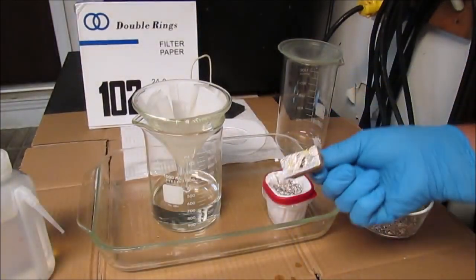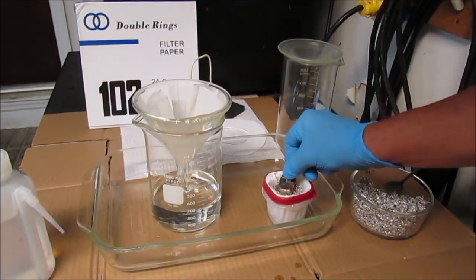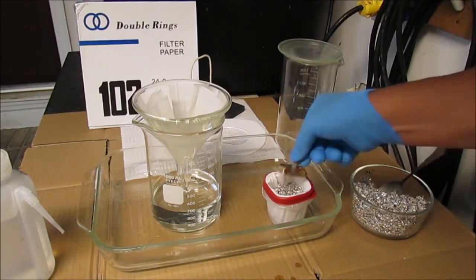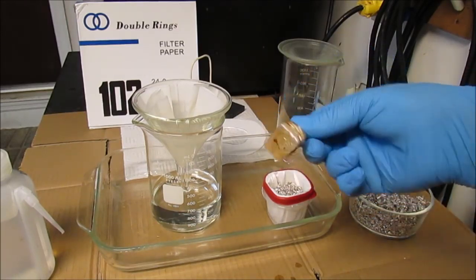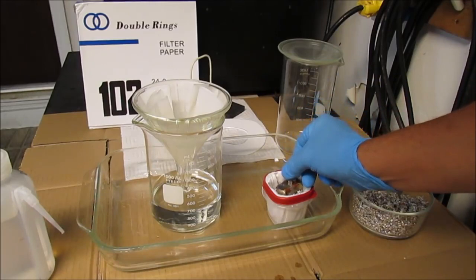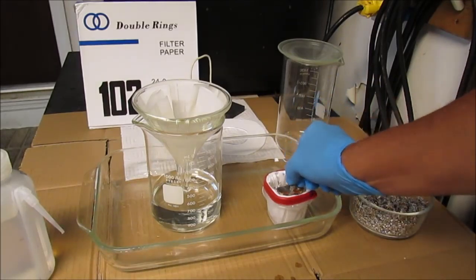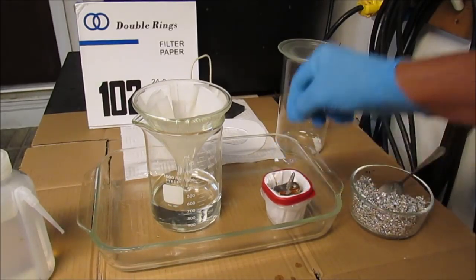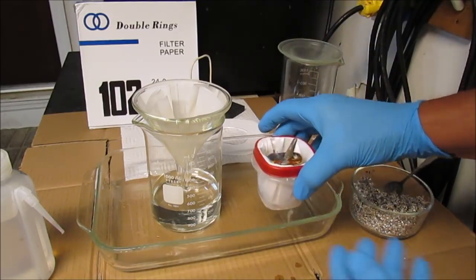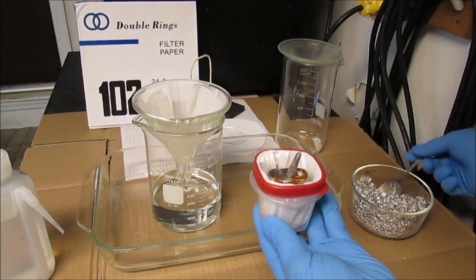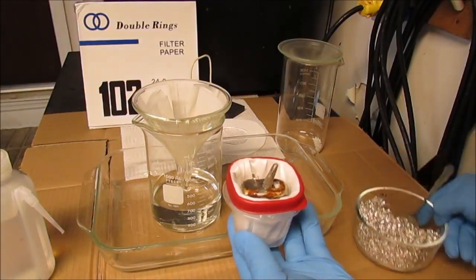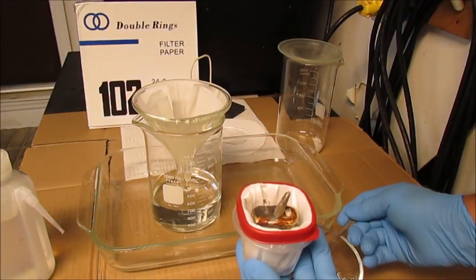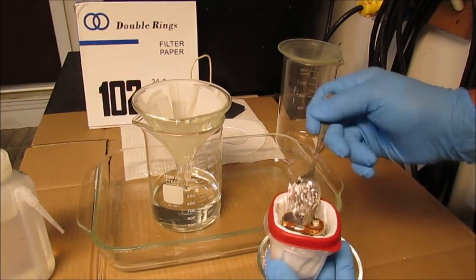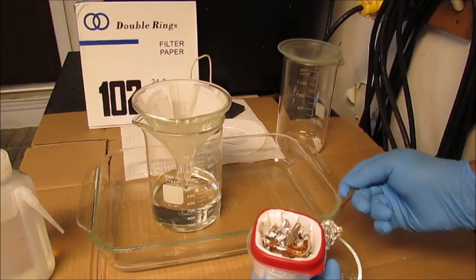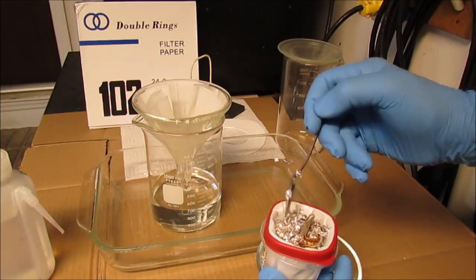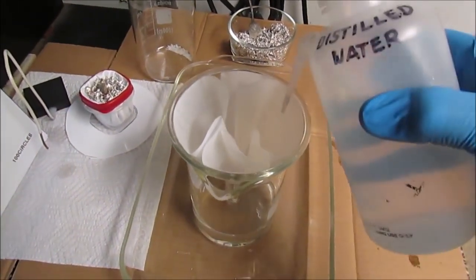Now I'm going to stick the anode bar on top of the silver that's in the basket there. I want that anode bar nice and chunky so that as the silver dissolves in the anode basket here, it presses the silver on top down into the bottom that's submerged in the electrolyte. I'm going to go ahead and bury this in impure silver shot to make sure we get a good connection, good electrical contact. All the electrolytes pass down through this filter.